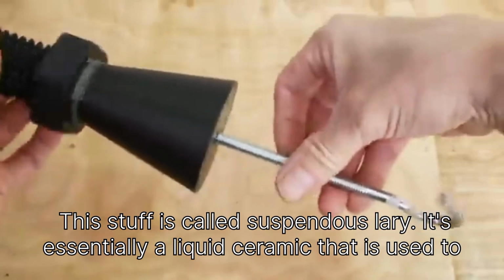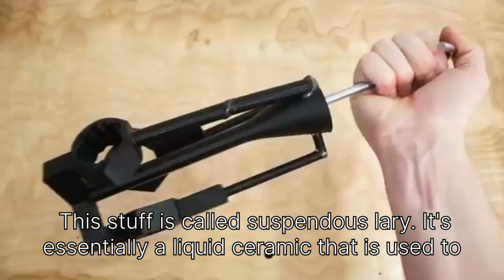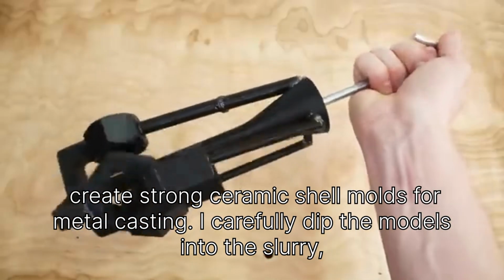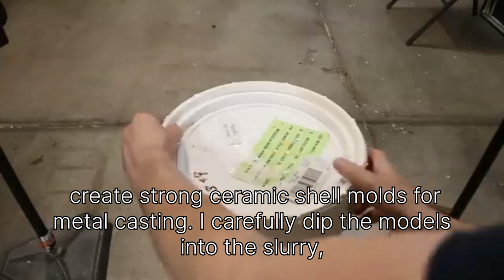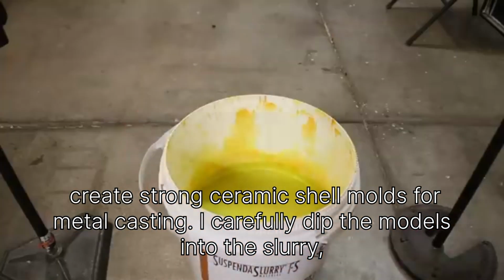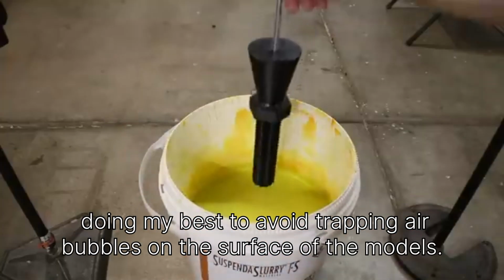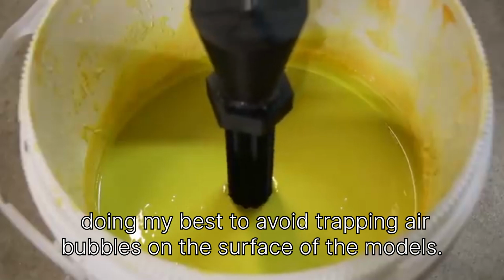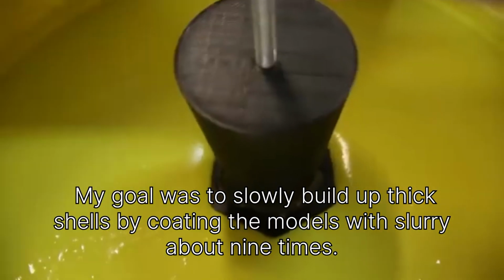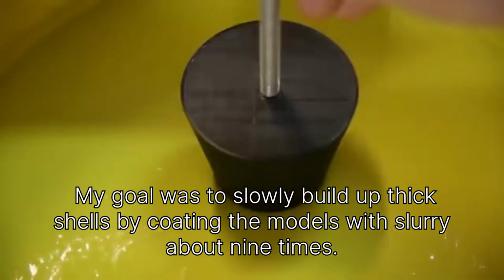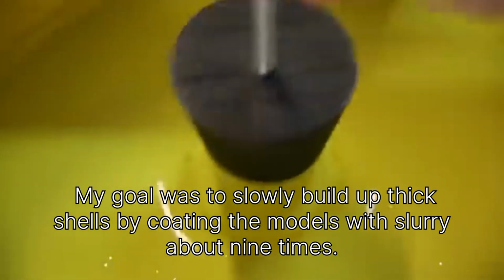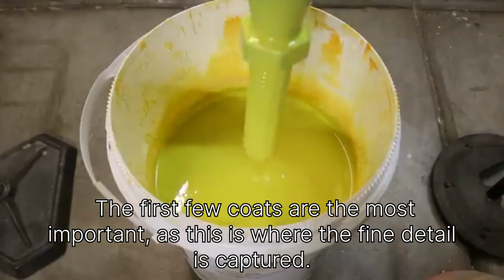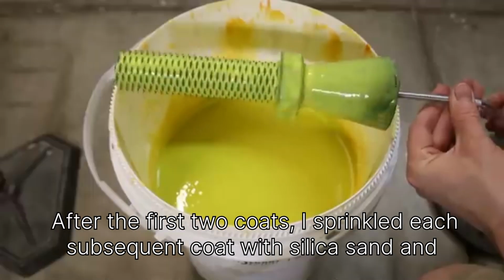This stuff is called SuspendaSlurry. It's essentially a liquid ceramic that is used to create strong ceramic shell molds for metal casting. I carefully dipped the models into the slurry, doing my best to avoid trapping air bubbles on the surface of the models. My goal was to slowly build up thick shells by coating the models with slurry about 9 times. The first few coats are the most important, as this is where the fine detail is captured.